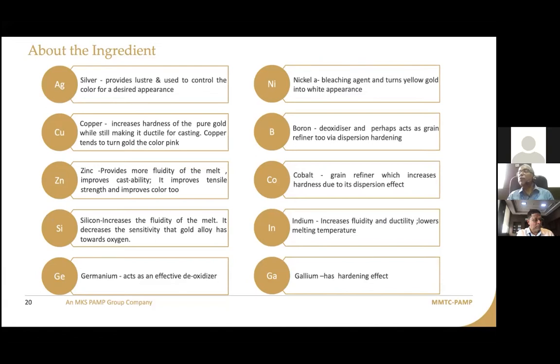Germanium is a new age deoxidizer, much more effective than silicon. It can be added independently or in conjunction with silicon, and it gives the best deoxidizing effect till now among all the deoxidizers used. But it is costly, and of course, over a certain quantity, it will have its own deleterious effects in terms of forming inclusions.